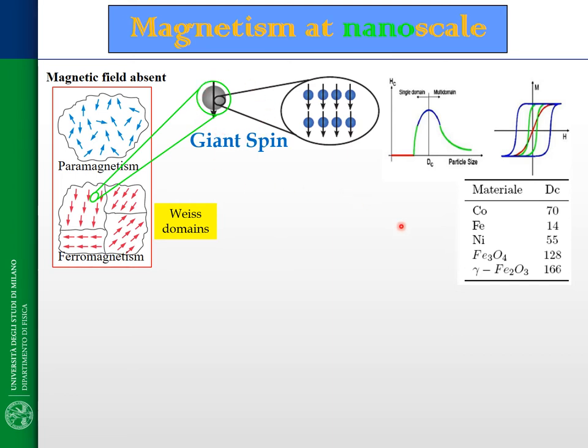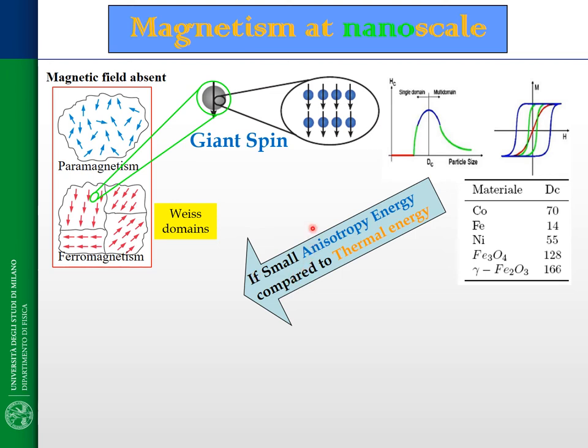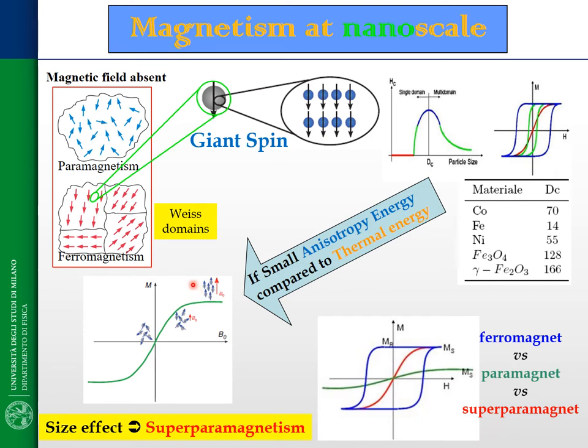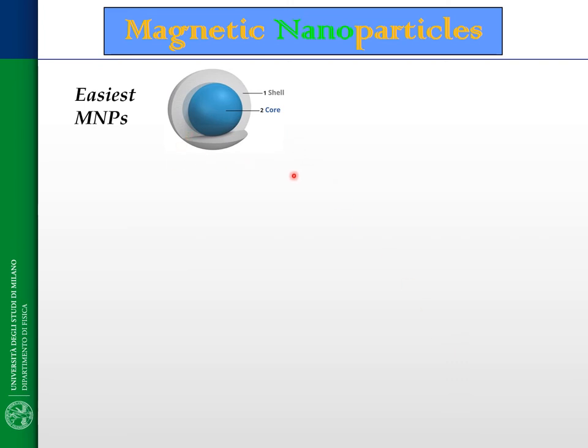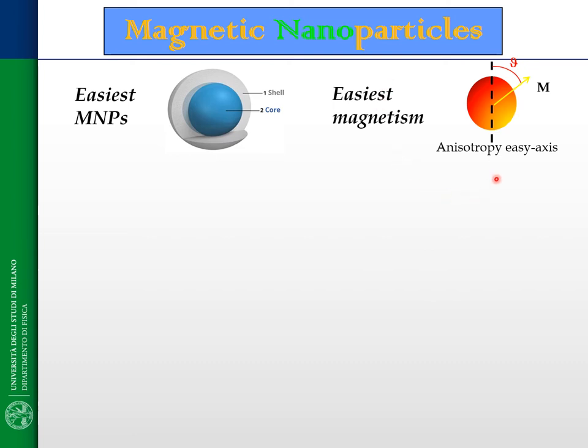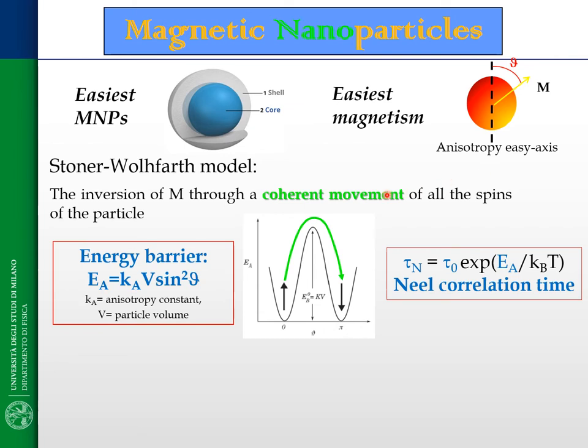So we can obtain the giant spin for the nanoparticles. In the case that the magnetic energy of the nanoparticles is comparable to the thermal energy, we observe the so-called phenomenon of superparamagnetism, where we have a material that behaves like a paramagnet but with a really high magnetization. In the easiest case of the core-shell nanoparticles, we have only one easy axis for the magnetic anisotropy and only two energetic minima. We can imagine that there is an inversion of the magnetization through an energetic barrier characterized by the magnetic anisotropy and the dimension of the nanoparticles, and this movement can be described by the Néel correlation time.